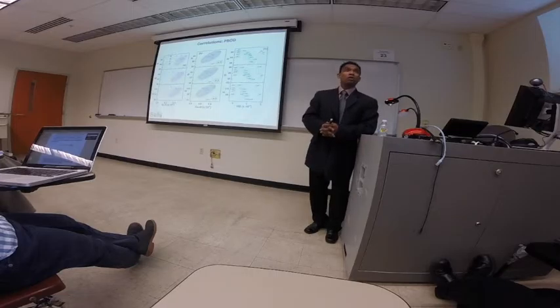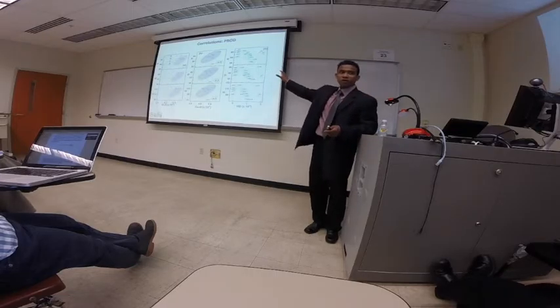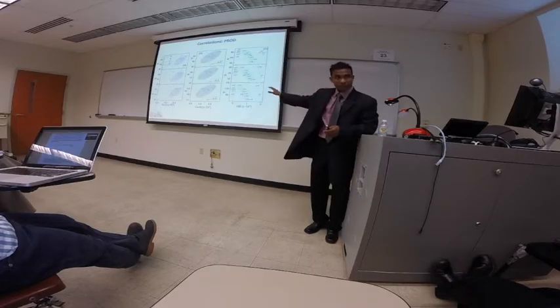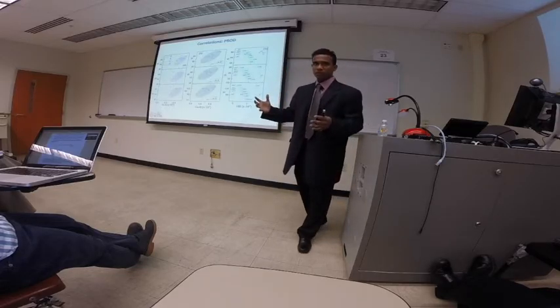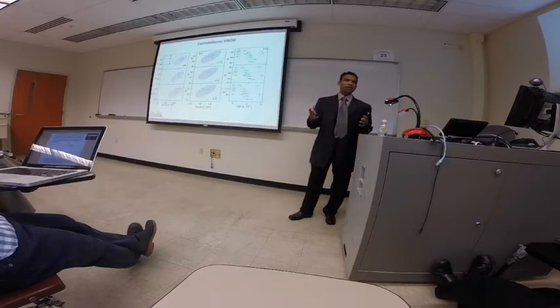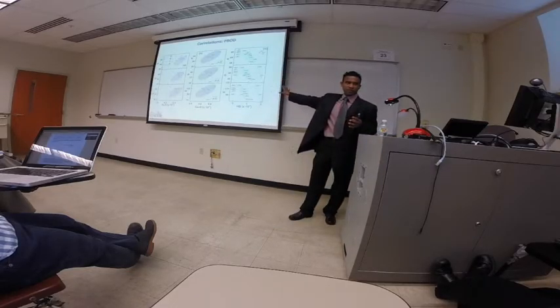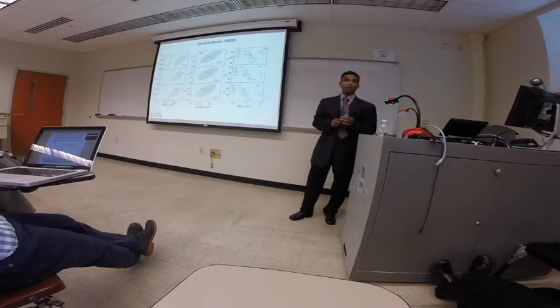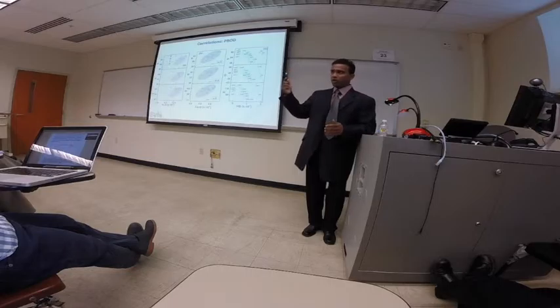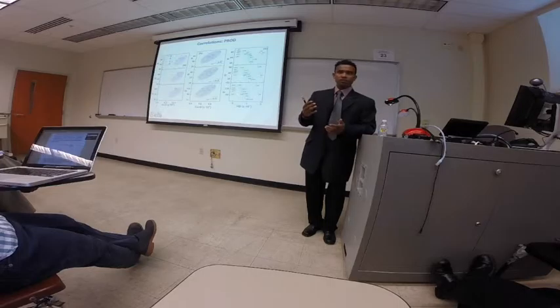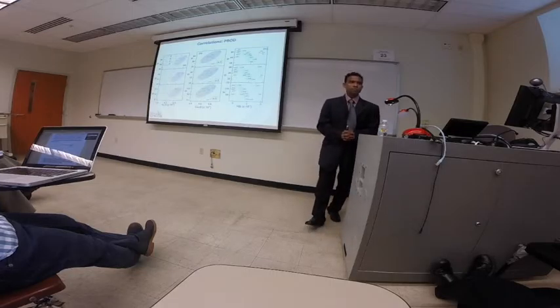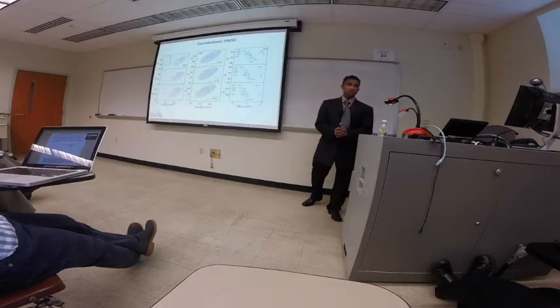Yeah, that's because it's amorphous in all directions. But even the crystals, even these crystals, the ones that people actually observe. So we didn't publish this, but we studied this and found out that the class of crystals we had was not anisotropic at all. Although some researchers went on about the anisotropy because it's a layered compound. So anisotropy comes into play, but in reality it doesn't, not too much. There is apparent anisotropy, but in terms of mechanics, the impact of that visual anisotropy is pretty minimal, is what you're saying. Yes. Okay.